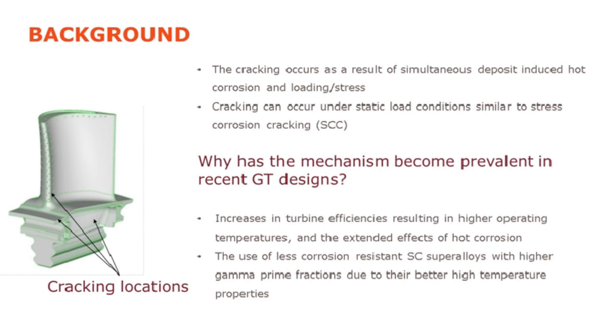And I think a very good question is, why has this mechanism become prevalent in recent gas turbine designs? I think there's a couple of reasons for that. The first is increases in turbine efficiencies, driving up operating temperatures due to your Carnot cycle, and we see the extended effect of hot corrosion. So really we're pushing the boundaries and trying to improve efficiencies of these turbines, or running some different fuels, hydrogen, etc., which might need us to run at higher temperatures, and that can really extend the effects of hot corrosion into areas where we wouldn't typically see it.